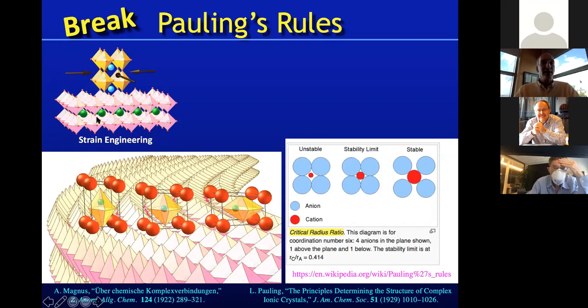Imagine the perovskite substrate that's pink and green here, having a spacing that's a little bit smaller than the atoms that we're raining down on top of it. And so those atoms form with biaxial compression. It's biaxial because in my simple cartoon here, I'm thinking about putting a cubic perovskite on top of a cubic substrate. And so in order to make it fit, we squish it from both in-plane directions. So it gets strained in plane, and in the out-of-plane direction, it's allowed to relax, so it's stress-free in the out-of-plane direction. But this is a way of imparting biaxial strain.